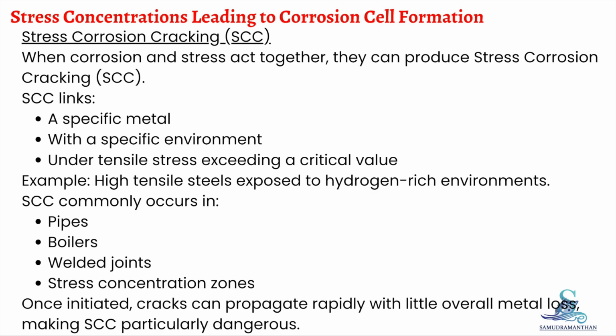When corrosion and stress act together, they can produce stress corrosion cracking, commonly referred to as SCC. Stress corrosion cracking links a specific metal with a specific environment under tensile stress exceeding a critical value. A typical example is high tensile steels exposed to hydrogen-rich environments. SCC commonly occurs in pipes, boilers, welded joints, and stress concentration zones. Once initiated, these cracks can propagate rapidly with very little overall metal loss, making stress corrosion cracking particularly dangerous.